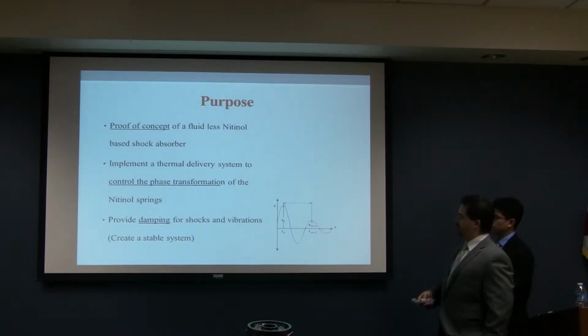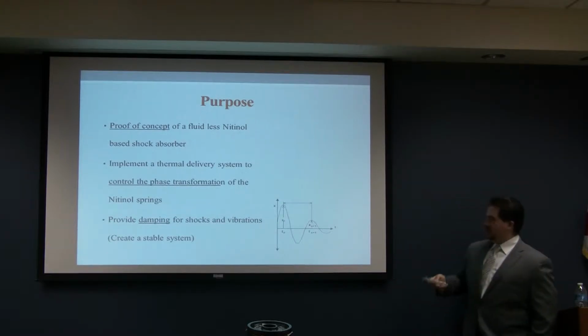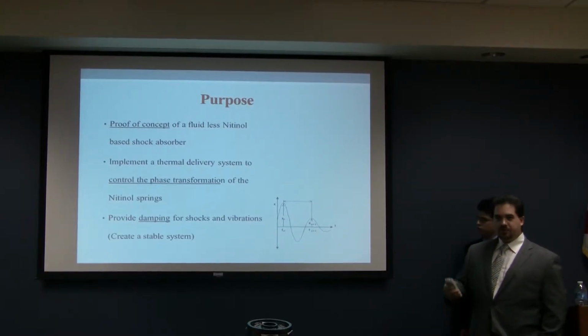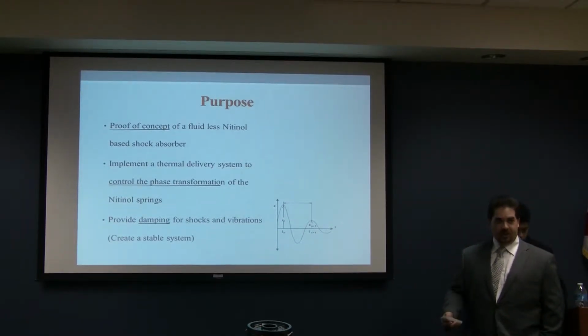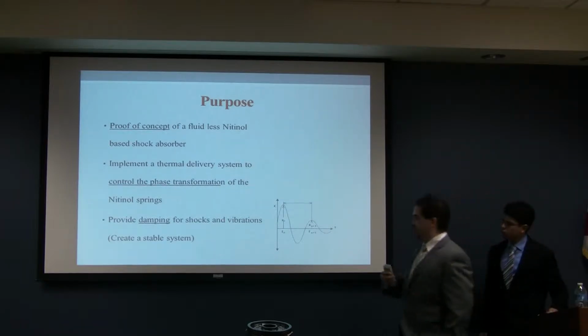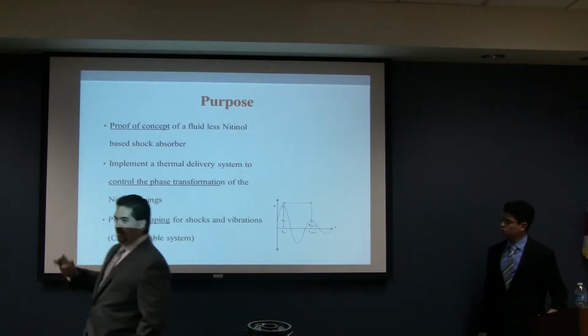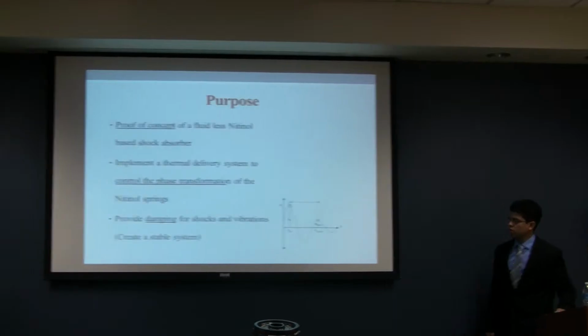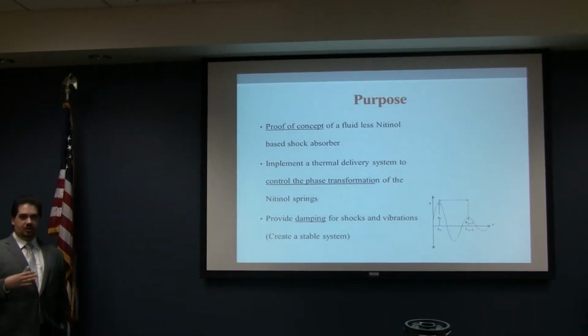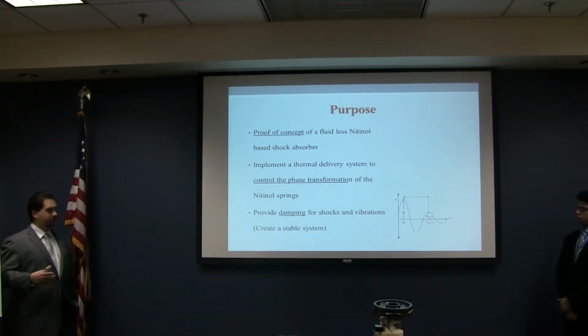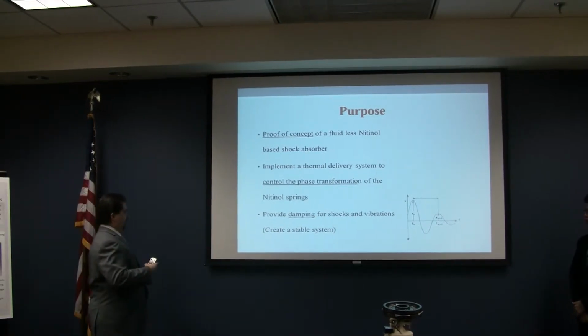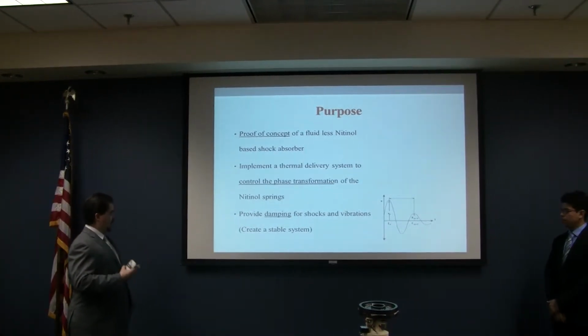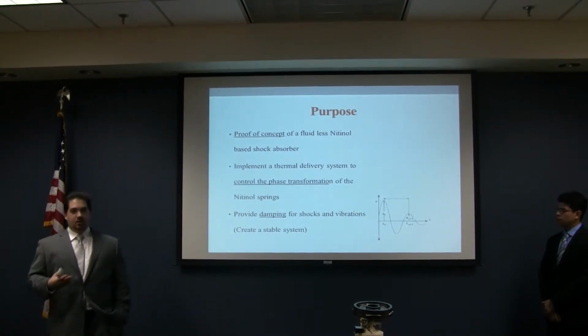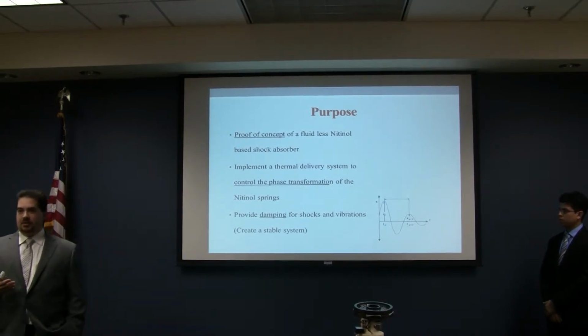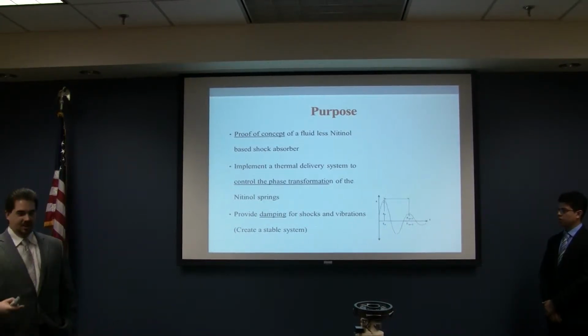The next part was to implement a thermal delivery system to control the phase transformation. We were successful in this ultimately. However, it would have been nice if we could have a feedback loop, so that way we could actually fix the temperature at a desired level. And last but not least was to actually change the damping ratio by altering the physical state of the material, changing from martensite to austenite. Next slide.